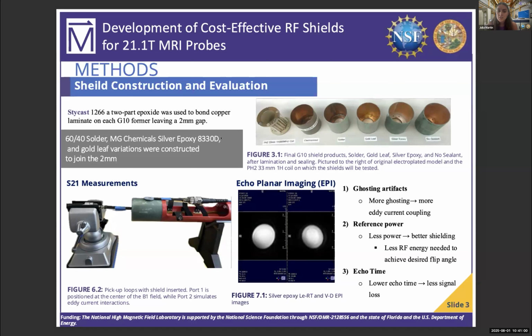To evaluate shield performance, I measured the S21 parameter using a vector network analyzer and near-field pickup loops. As you can see in figure 6.2, this bottom pickup loop is placed into the center of the B1 field where the sample would sit, and this top loop rests on top of the RF shield simulating potential eddy currents.